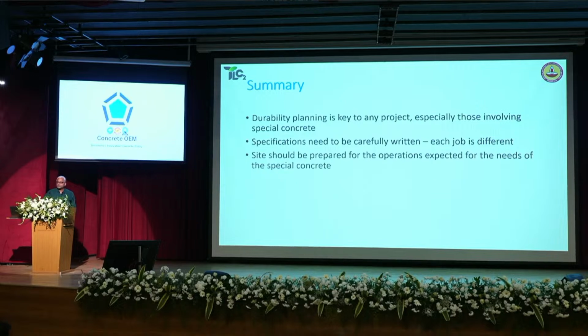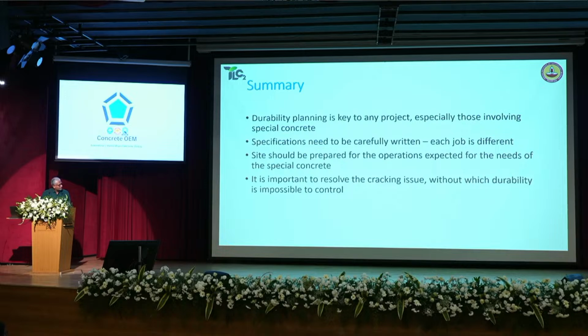Site should be prepared for operations expected for the needs of the special concrete. Again, if the special concrete is likely to result in very high temperatures, the site should have an ice plant to ensure that the concrete can be supplied at a controlled temperature all the time. If the concrete has a propensity to crack, we have to take all possible measures to avoid plastic shrinkage cracking. And again, cracking is very important to resolve.